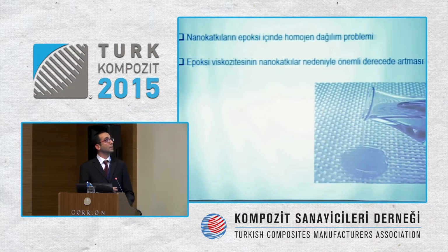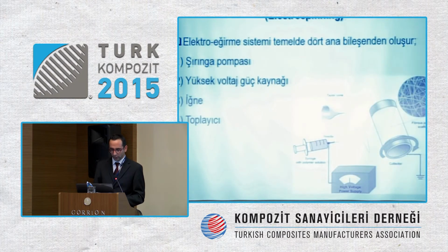And PVA nanofibers, for example, are mixed with epoxy, and mode 1 and mode 2 increase by double, and also the fatigue performance increases. But it's also difficult to homogeneously dilute nanofibers in epoxy, and the viscosity of the epoxy increases dramatically with these additives. And in composite manufacturing during infusion, it creates a problem.